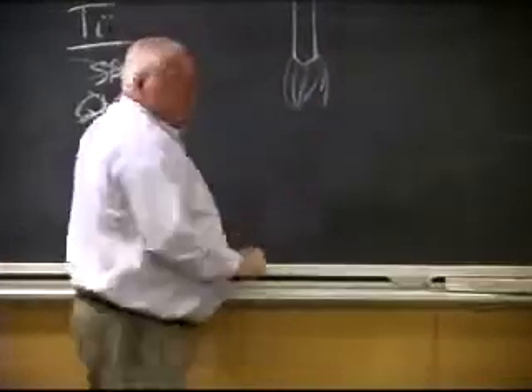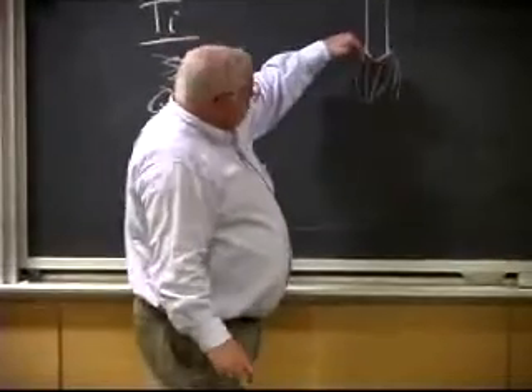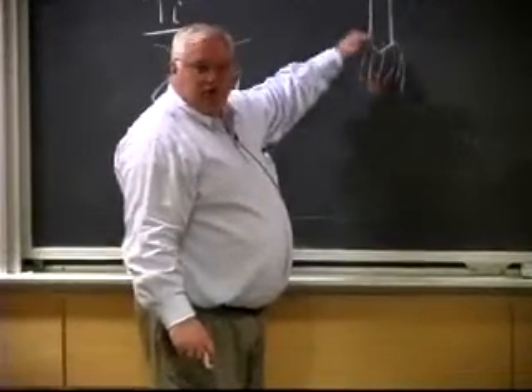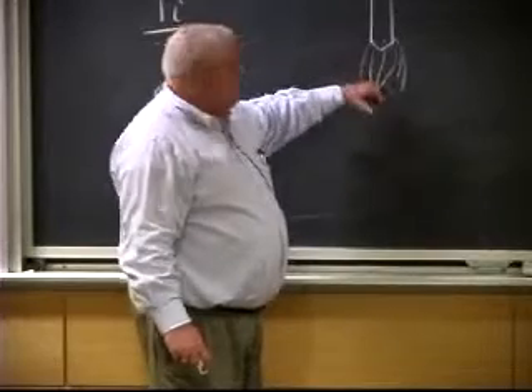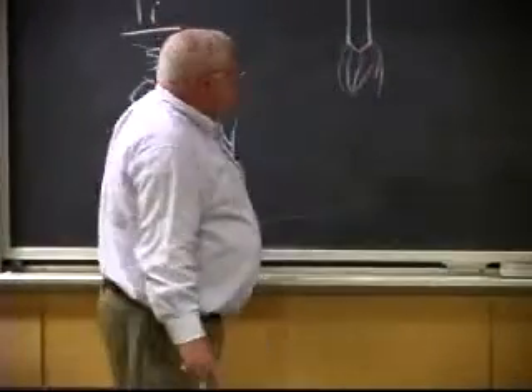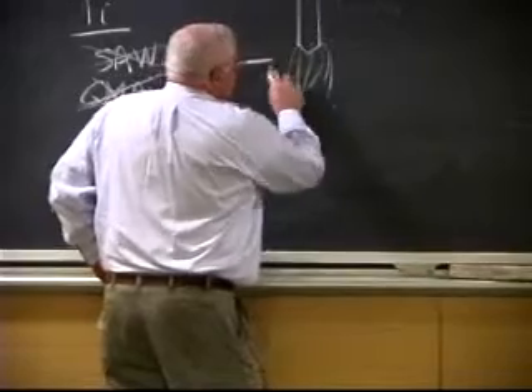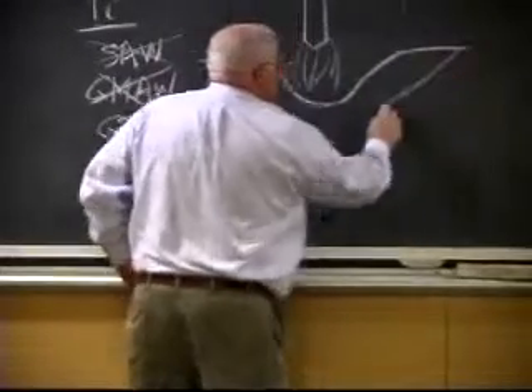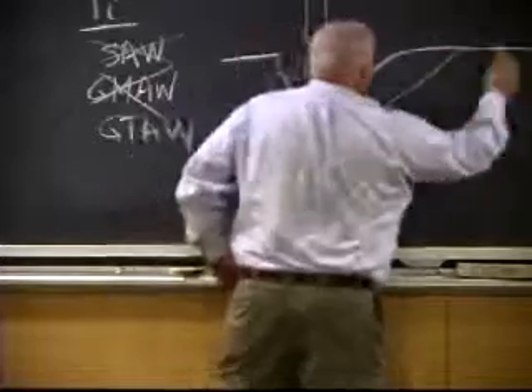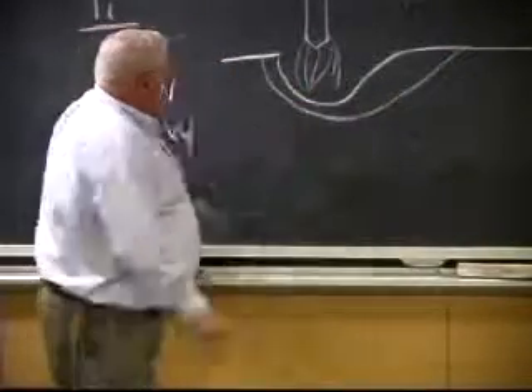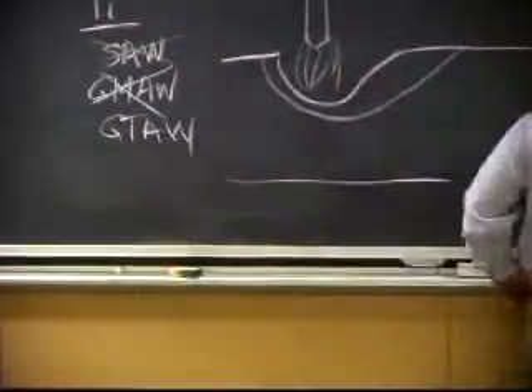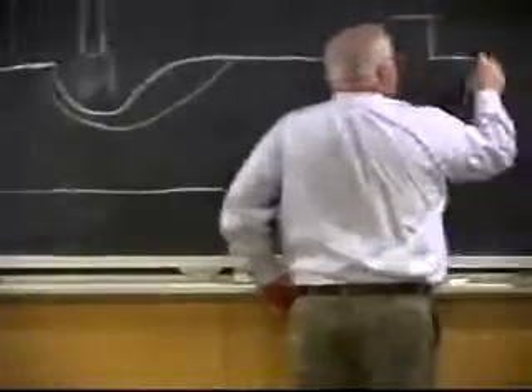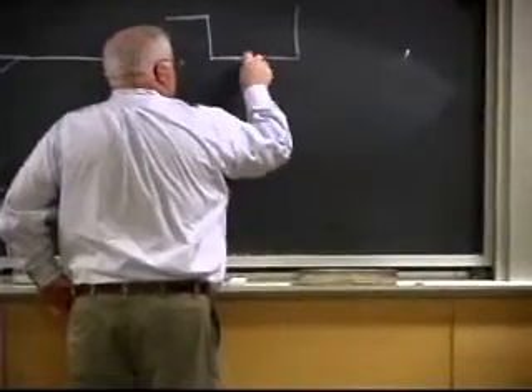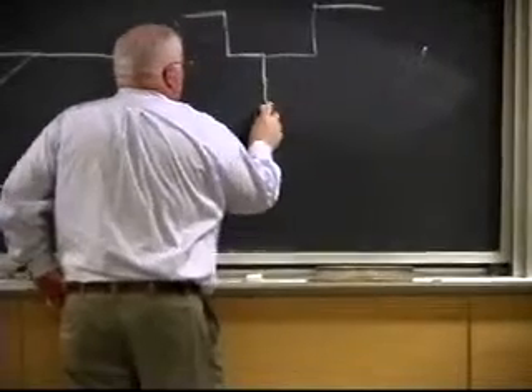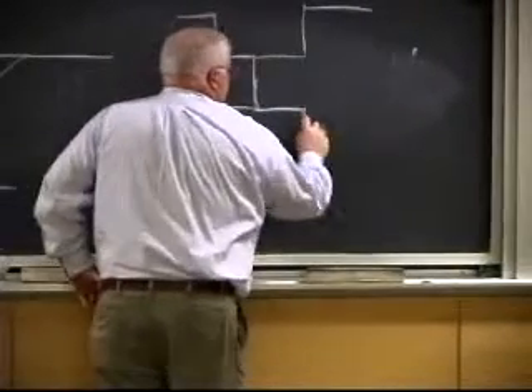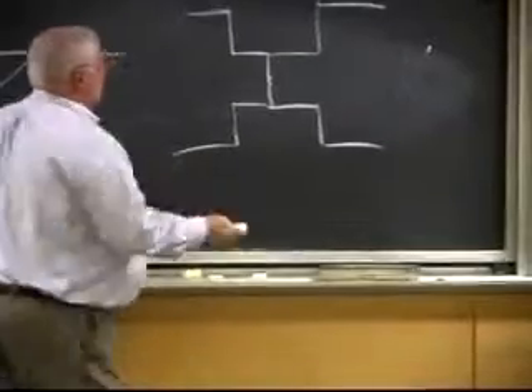And later this week, we'll talk about plasma jets. But there's a wind that comes off the end of this electrode that's proportional to the current. Actually, proportional to current squared. At 800 or 1,000 amps, you actually significantly depress the surface of the weld pool. So if this is your weld zone, you can just gouge a hole right in the liquid metal. And one of the techniques that was used, the Soviets could weld 2-inch thick titanium with a joint preparation that looked like this. And they do it at 1,000 amps or something on that order, I don't know exactly.